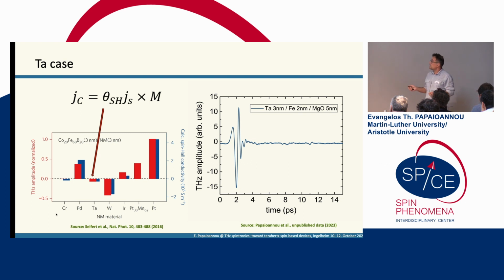And we made a series, and we were expecting that the tantalum 3 nanometers, iron 2 nanometers would have the highest signal, because we know, this graphic you saw also in some previous publications, that the terahertz emission is thickness dependent. We expect a maximum of the emission at a total thickness of 5 nanometers. And this is what we try to do.